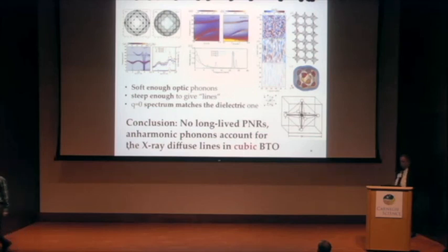Yeah, so our conclusion is that barium titanate in the tetragonal phase has a clear distinction between lines: the time scale of the order-disorder dynamics, which is jumping between the minima, and the fluctuation of the order parameters, which are small fluctuations, the ones described in terms of phonons. But in the cubic phase, it's not the case. It's very hard, and I don't know at the moment how to distinguish between them.